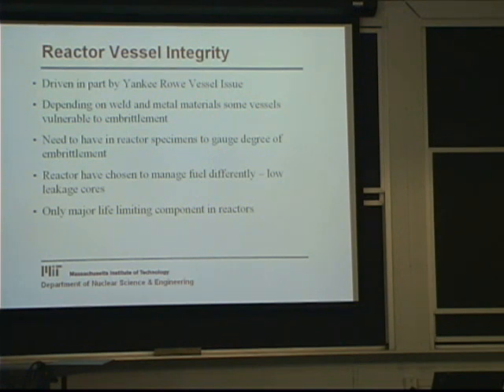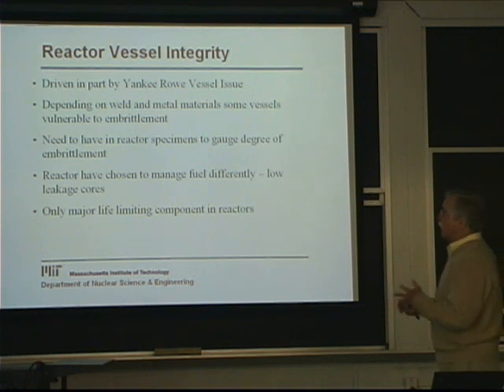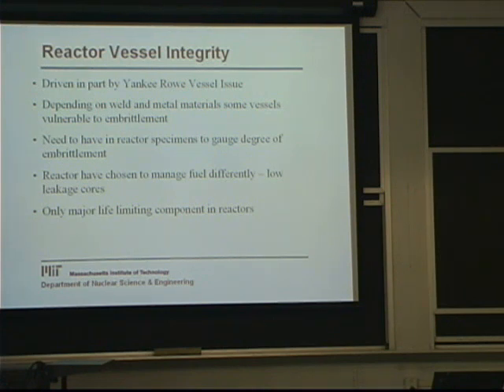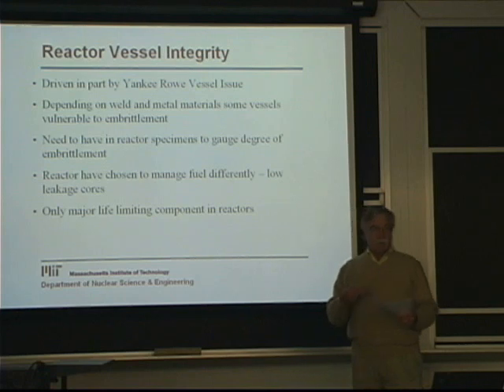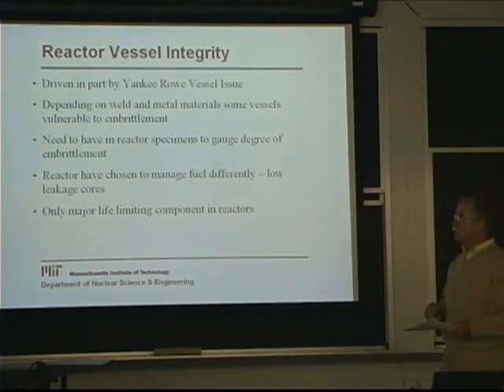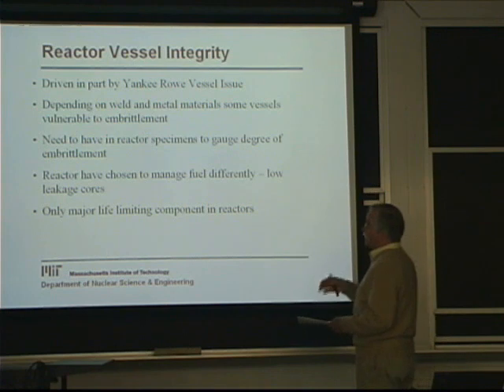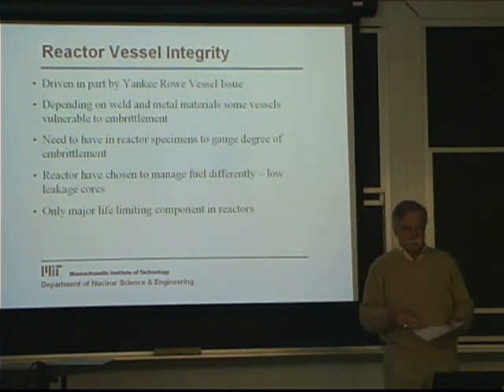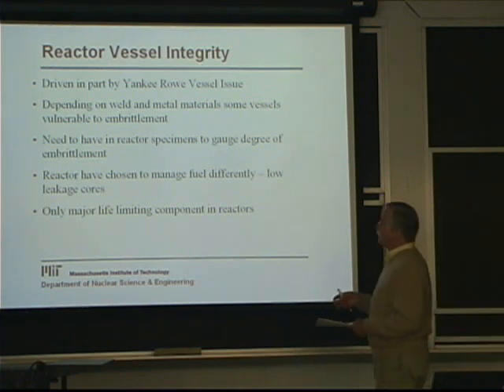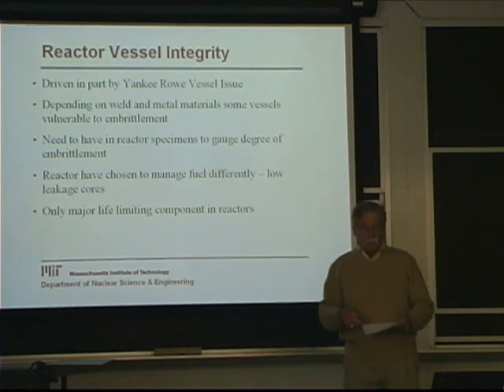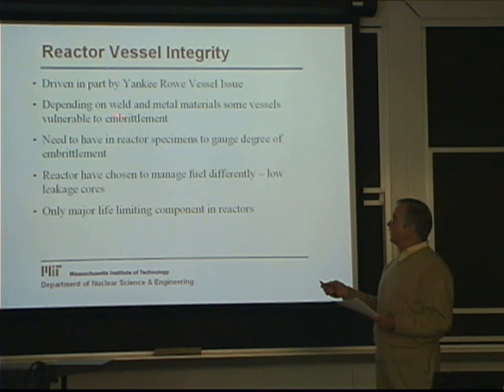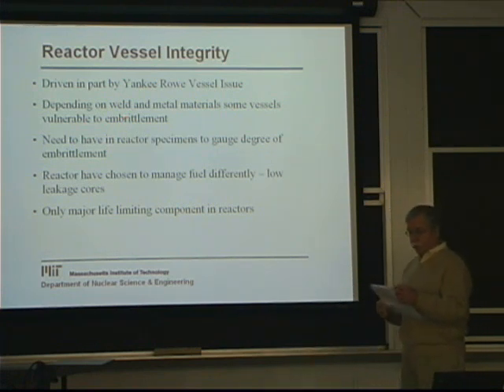Typically, these specimens are located in a number of places in the core, where they can get irradiations over time. What we had at Yankee was that we were trying to go for a license renewal, and one of the justifications for continuing to operate past 40 years of operation was that we needed to show the vessel was sound. Well, in our attempt to defend it, obviously it depends on the weld material and the metal, because it depends upon the chemistry of the metal; you have more or less susceptibility to embrittlement. As I recall, it was copper content, some nickel content, and basically it was very key to be able to understand what the vessel was in fact made of, because the performance was significantly different.